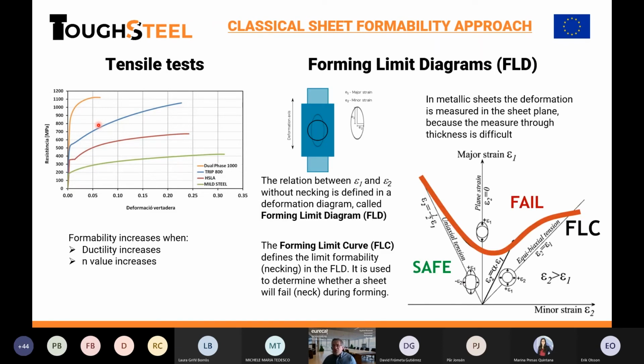And traditionally, the sheet forming sector is also using what is called the forming limit diagrams. Because in metallic sheets, the deformation is difficult to measure through the thickness, so it is usually measured on the surface. So using DIC techniques, it's possible to follow the strain distribution during forming. Following this strain distribution from a dot, from the major and the minor strain, we can plot a curve where we can see the areas that are failing or necking or where fracture is happening, and we can also see the areas where the forming is safe. So this is what we call the FLC curves.